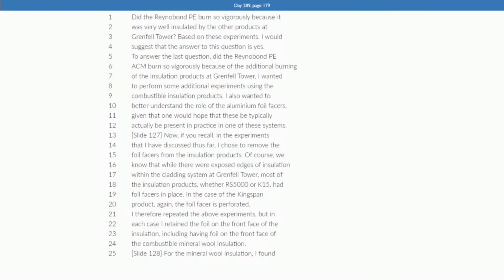Thank you. And if we go to line 21, you say there, and you're describing the experiments where you remove foil facers from the insulation products. And if we pick it up at line 15, you say, of course we know that while there were exposed edges of insulation within the cladding system at Grenfell Tower, most of the insulation products, whether RS5000 or K15, had foil facers in place. In the case of the Kingspan product, again the foil facer is perforated. I therefore repeated the above experiments, but in each case I retained the foil on the front face of the insulation, including having foil on the front face of the combustible mineral wool insulation.